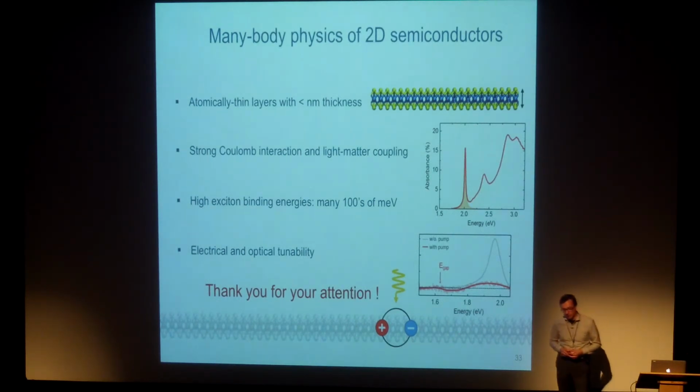Basically, one way nowadays available is using strong and pulsed mid-infrared terahertz sources to probe the intra-excitonic transition. And it was done quite successfully in indirect gap materials, silicon germanium, for example. That would be a way to do it. Another way maybe is some sort of photoemission spectroscopy, maybe 2PPE, to map out the conduction band.